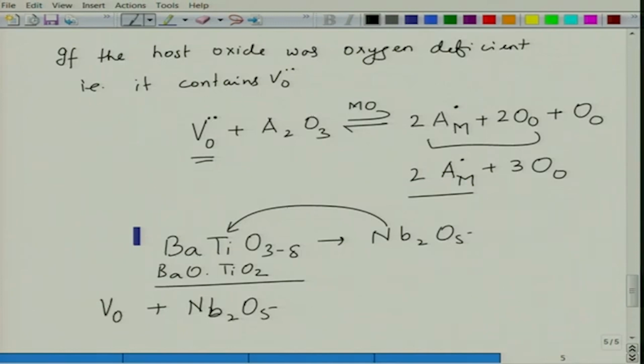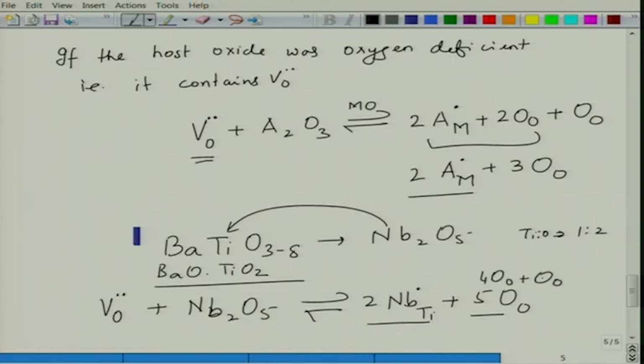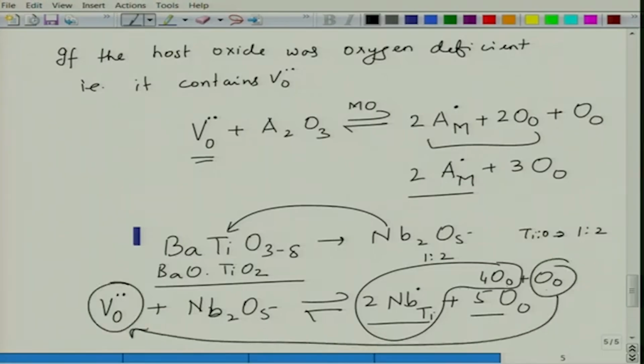So, if you put niobium in this Nb2O5, you have vacancies of oxygen in the system. So, 2 niobiums go to titanium site plus 5 oxygens go to oxygen site. So, this niobium will be positively charged. So, out of these 4 are related to titanium, because Ti to O is 1:2, right. Okay. So, out of these 5, you can write this 4Oo plus Oo. So, 4, this is site balance 1:2, and this is compensated by this extra one. So, this is how barium titanate is made more resistant.